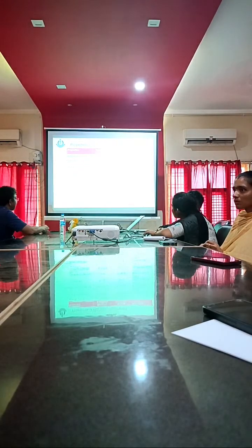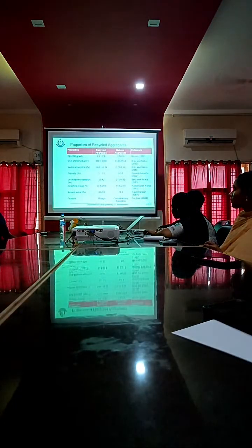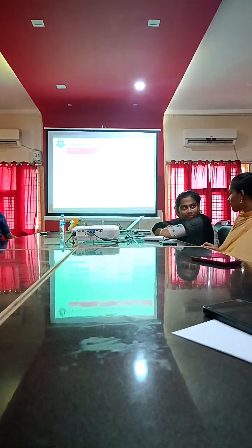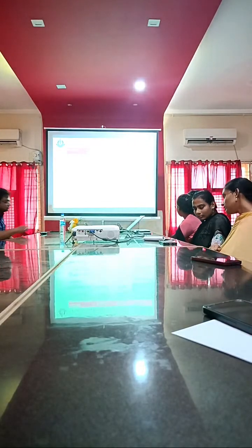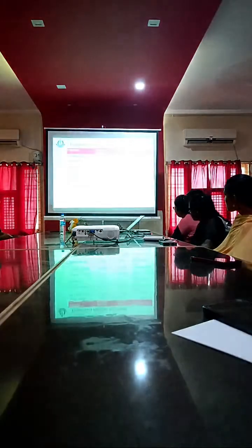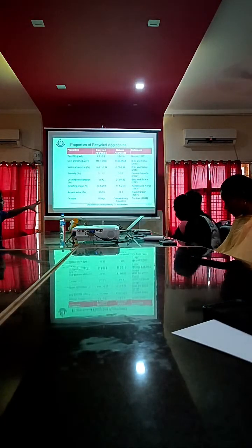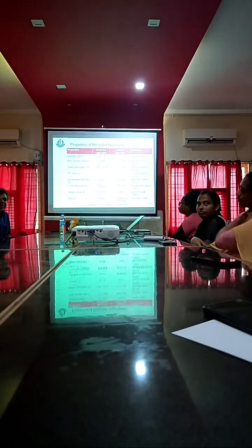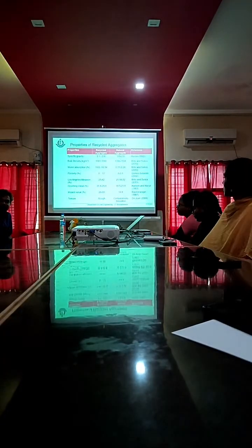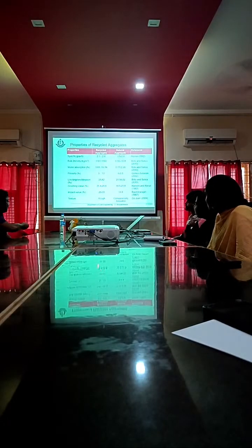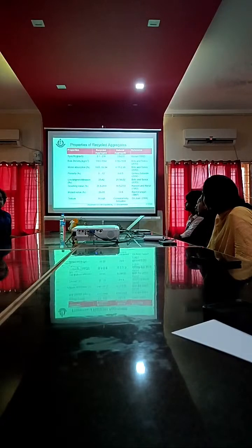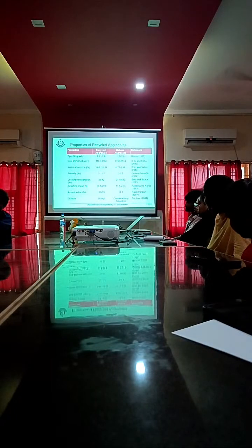Sir, the crushing value and impact value are much more compared to the natural aggregates. Yes, crushing value, it's a weak aggregate. How to determine the crushing value? The more the crushing value, the weaker the aggregate is. Understand? Due to the porosity. Yes, it is porous because of the attached water and all. Already it has undergone some life. And what is the highest permitted value as per IS 456? What is the limit for this? Crushing value should be less than 30%. So the aggregates may satisfy, they may not. If they satisfy that, you can go for 100%.